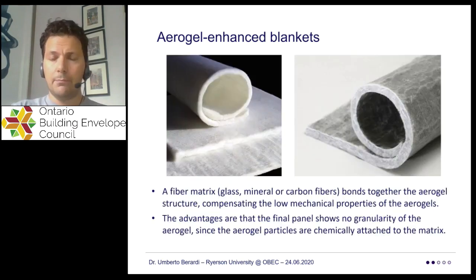An aerogel-enhanced blanket is basically a normal blanket, such as fiberglass or actually any fiber material, in which you put a lot of the gel when it was still liquid, and then you evacuate the liquid portion. And so the structure of the aerogel gets trapped into the bonds of the fibers.